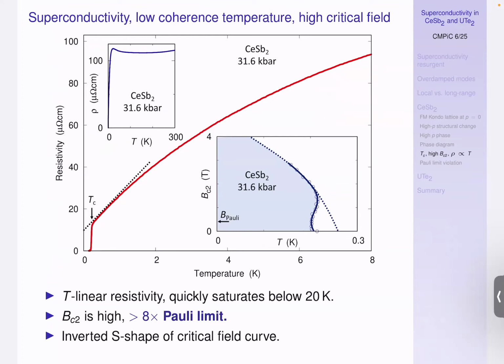So this is the upper critical field of cerium antimony 2 versus temperature. We start out at about 220 millikelvin, and by now the critical field has actually been measured in a dilution fridge down to lower temperatures. So this dotted line is actually confirmed, and the critical field is of order 4 Tesla. That seems high if you consider that the transition temperature is only 200 millikelvin, because there's a limit on the critical field, the Pauli limit, which says that about twice the transition temperature in Tesla is what you would expect to be the limiting field. So it should be 0.4 Tesla, yet it's 4.